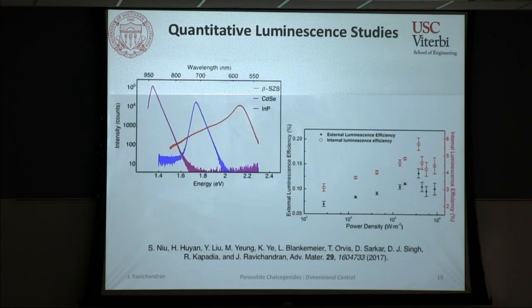Not only that, we took these systems and we tried to do quantitative luminescence to get a sense of how well they do in terms of the external quantum efficiency. And what we found was that if we use the same irradiation conditions, indium phosphide and cadmium selenide single crystal wafers show PL curves that can be put on the same curve as our beta SZS. Of course, we are not saying that our material is better than any of the III-Vs, but in terms of quality, you can at least put them on the same curve, which is actually pretty impressive for the first generation material.